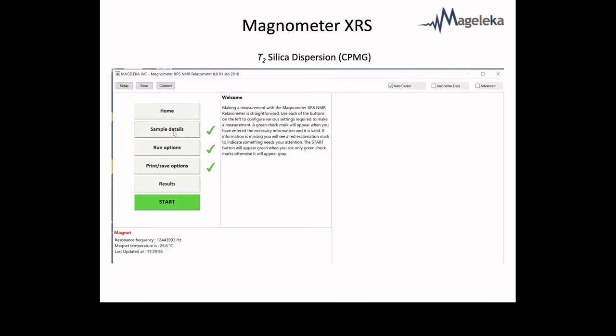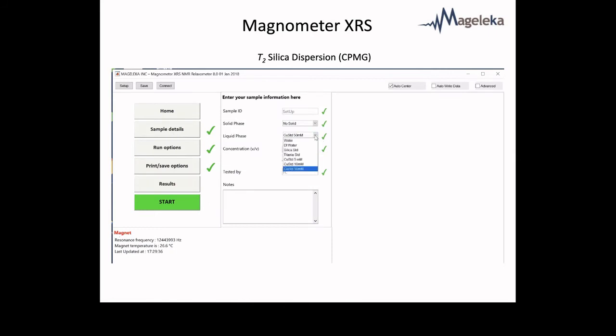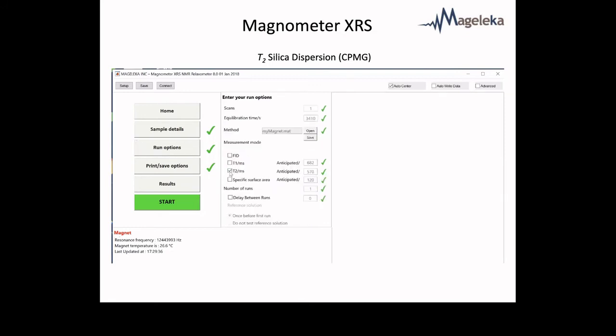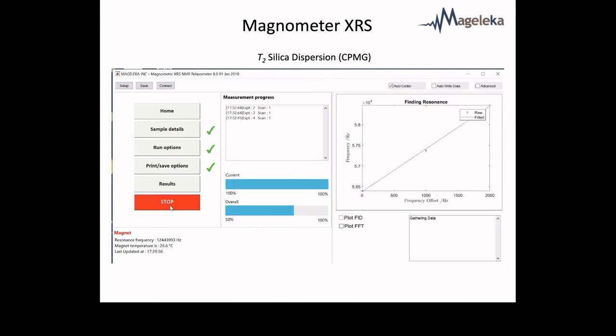Okay, so the first thing that happens is we go on the sample details and we set some parameters. We say this is going to be silica and water. We put in the concentration, 5%. We go to run options and we choose T2. And we want to measure surface area, so we click that and then we press the start button. So the first thing we do is the machine goes on resonance. You can see that's relatively quick. And then we have to wait to get the experimental data.